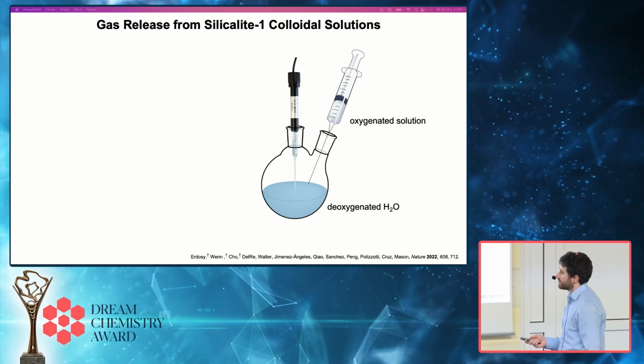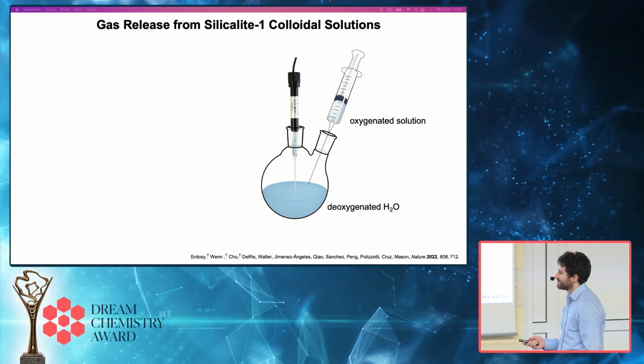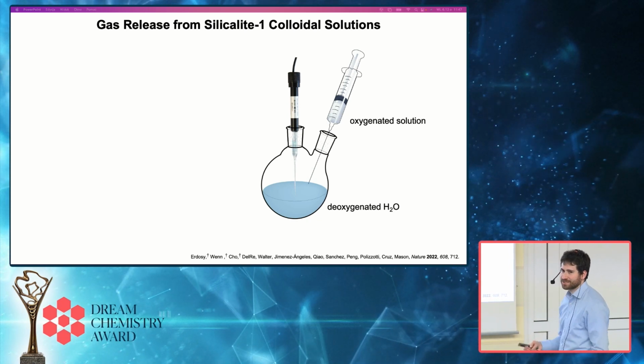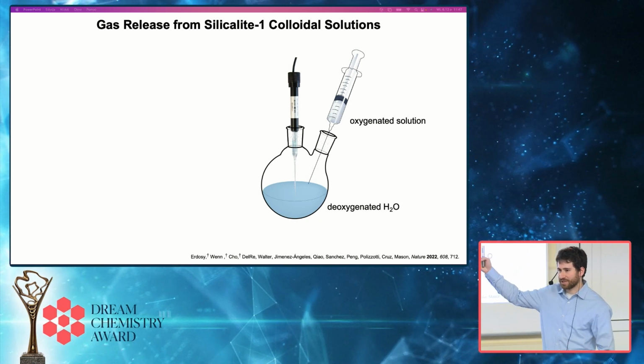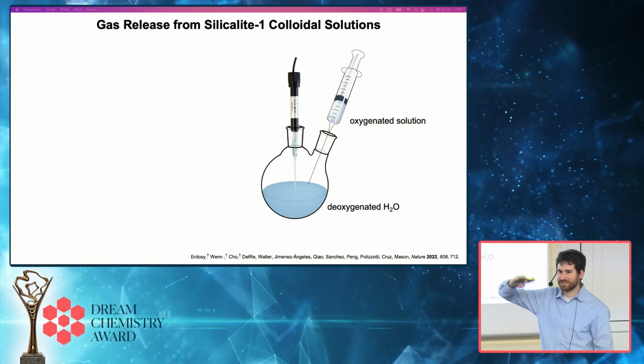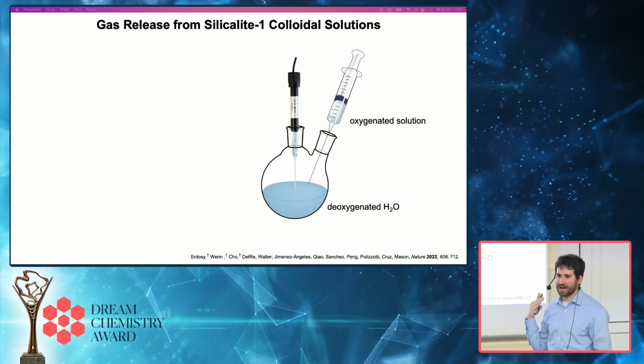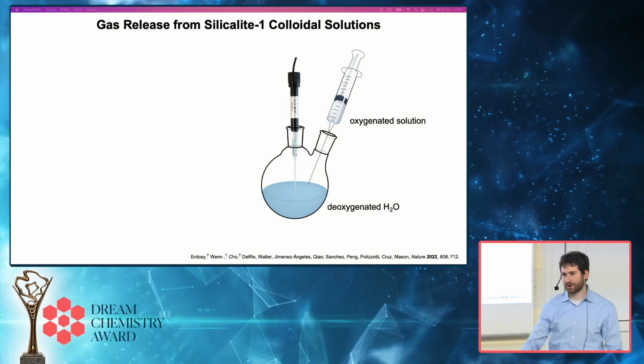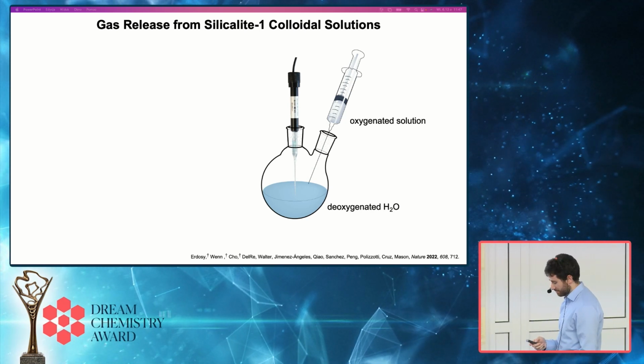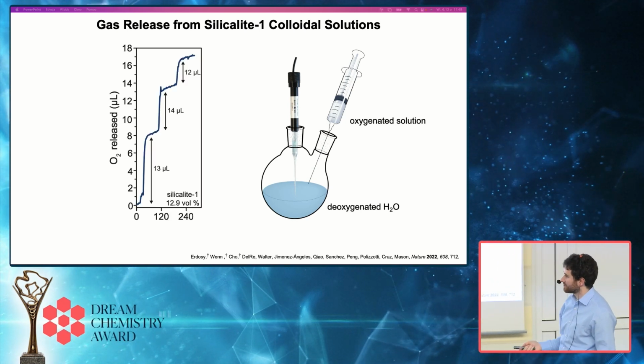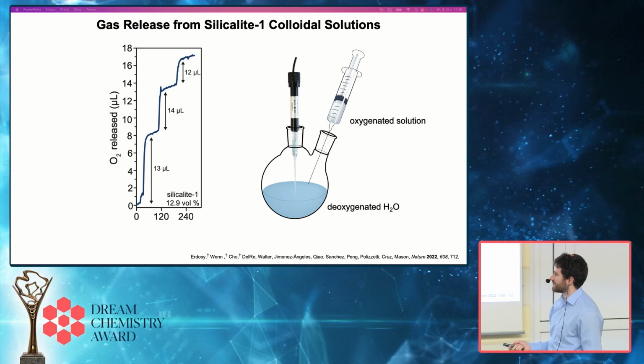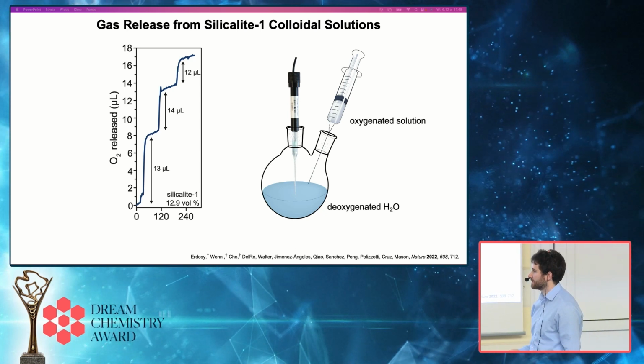What happens here is that, say we equilibrate at 1 bar of oxygen. Here we have 0 bar of oxygen, so there's a partial pressure or concentration gradient between our oxygenated solution and our deoxygenated solution, and that drives the desorption of oxygen from the particles into the surrounding solution. And so we can use an oxygen electrode to quantify exactly how much gas is released as we inject different quantities of these solutions.